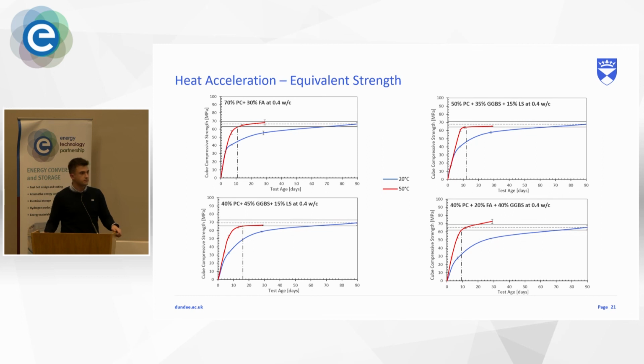Do you have any understanding of the strengthening mechanism which fly ash provides to the concrete material? With concrete hydration and complicated chemistry, there are different phases to it. We know that fly ash starts to be reactive after about, I can't remember what it is, I think it's a week or 14 days. That would align well with that theory here, because we know that roughly after, I think, 7 days, the fly ash phase kicks in, and that is what keeps the hydration going.